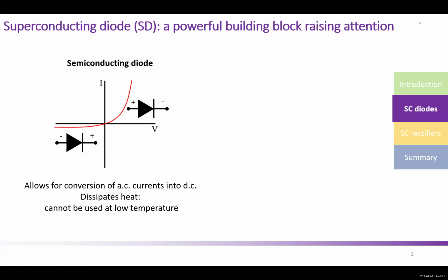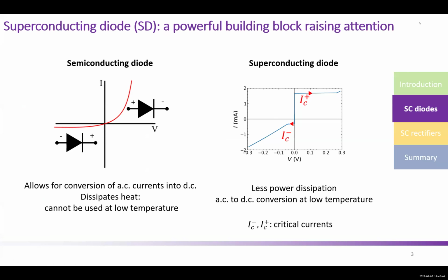So coming from the semiconducting diode, you have this non-reciprocity of the response. So you have this very large asymmetry between positive and negative voltage, which allows for converting AC currents into DC. But the problem is that it is resistive, so it dissipates heat. So we need to look for an alternative that can work at low temperatures, and that is what we call a superconducting diode. As some of you know, superconductors are materials that can carry current without a resistance. That means that you do not have heat dissipation in that regime.